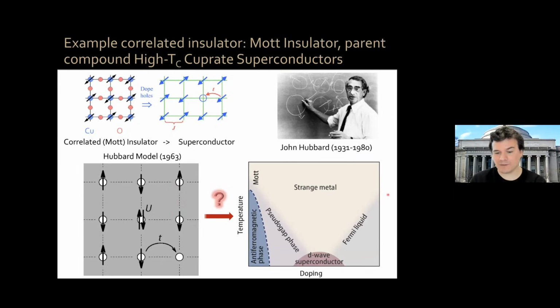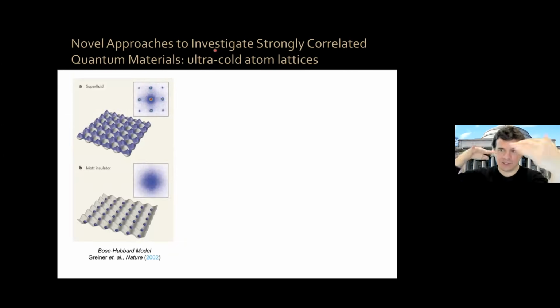And in this phase diagram of the cuprate superconductors, but also many other correlated materials, very few of the phases that we find here are actually completely understood theoretically. Now, these difficulties in understanding the physics of strongly correlated systems have led to alternative approaches to try to get insight into these systems, okay? And one of the most exciting ones is that of using ultracold atoms in optical lattices in order to investigate strongly correlated quantum materials. So if you take 2 lasers and you shine them at each other, okay, then you can create a periodic potential for atoms.